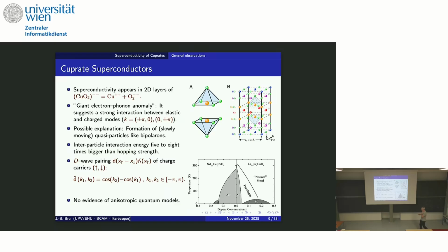So first of all, why do I stay in 2D? I say my system was 2D. It's not because I cannot do it in 3D. I mean, mathematically speaking, I could do it in 3D. But why I explain about 2D is because all these cuprates have one particular feature: they are made of layers of copper and oxygen each time, and the superconductivity lies in these layers. So the superconductivity is on the special layer of copper and oxygen. So that's why I restrict to 2D.